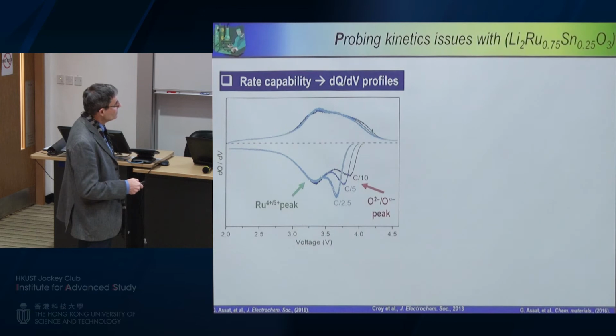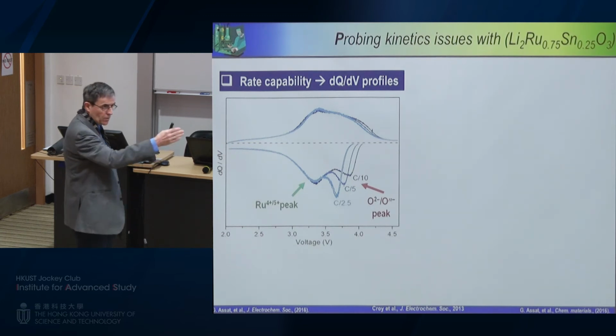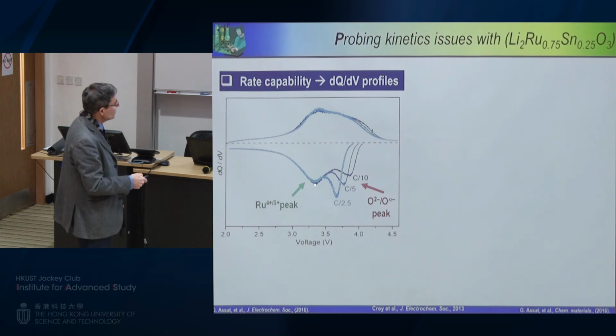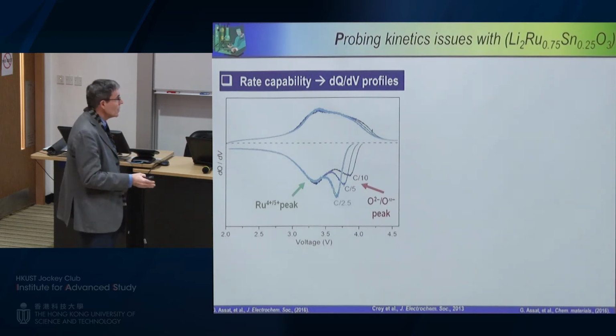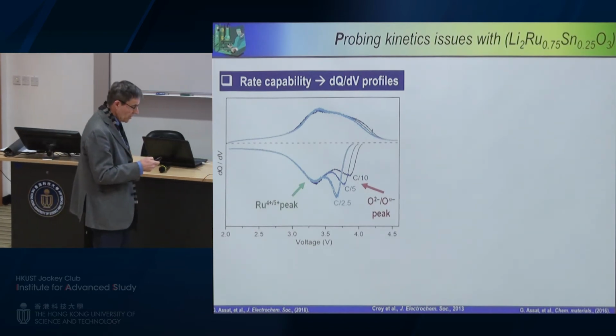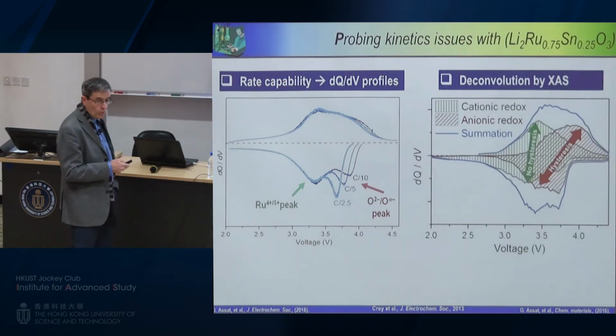Now, if I increase, or in this case decrease, my rate, as you can see here, you have a peak that is moving. So you can see, when I increase the rate, the cationic peak doesn't change, but the anionic peak is moving to higher potential, which means that in this case, the kinetics is very poor.